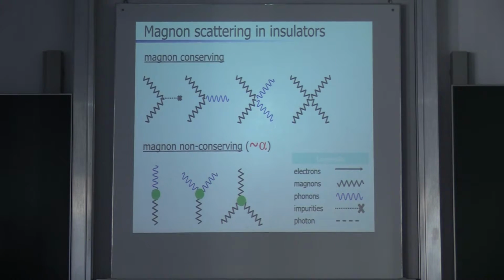But there are also non-spin-conserving scattering processes in which the magnons lose their spin, right? So for example, if you come in with a magnon and you emit a phonon, then the magnetic system loses angular momentum. This can also be written as a scattering process like that. So a magnon is lost. Now there are also three-magnon processes, where you come in with two magnons and they merge into a single magnon, which also corresponds to angular momentum loss.